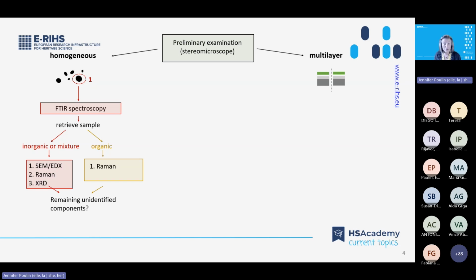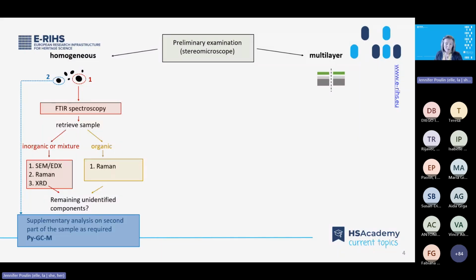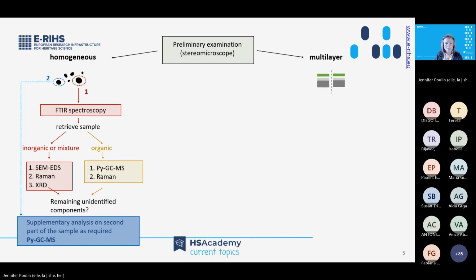If not all the components have been identified in the first fragment of the sample with those methods, a second piece of the sample can then be examined using additional techniques. For instance, if the IR spectrum of a varnish indicated that it was an acrylic copolymer, further analysis using PyGCMS would provide details about the polymer, as well as low concentrations of additives.